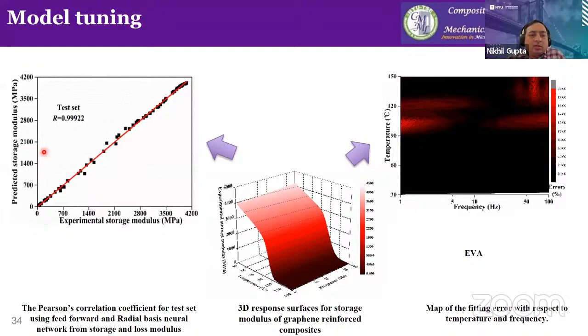Here is Pearson's correlation coefficient for the predicted storage modulus versus the experimental storage modulus from the trained data set. The R value is 0.999, which is pretty good. And then we can calculate the heat map for the error. This error map shows that there are some pockets where error is a little bit higher, but more or less it's within, I think, 3% for most part of this graph. So that's pretty good for the materials characterization field.